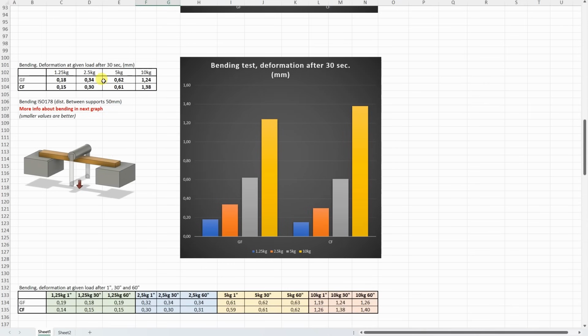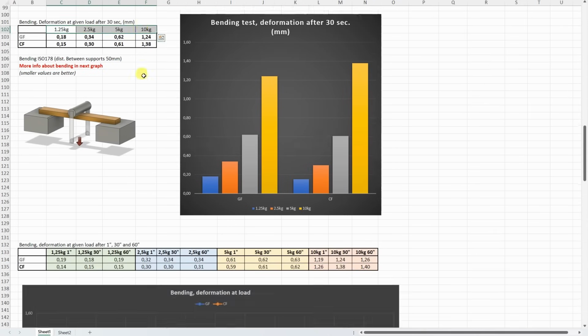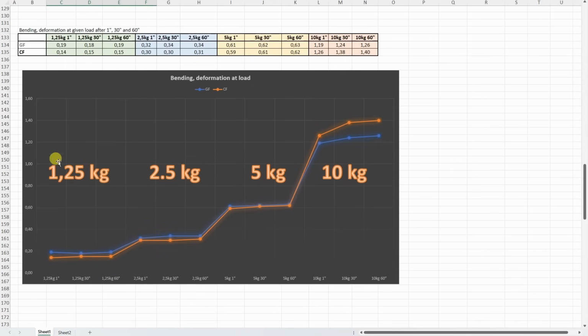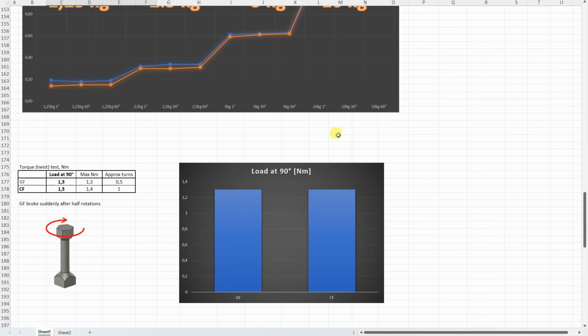And now the bending test. Now this is the deformation under these given loads after 30 seconds, but more interesting is this graph. And here we can see on smaller loads less deformation on the carbon fiber version, because here actually the base material resists to this stress. And look at this, on 10 kilograms, when actually it starts with the bending and the fibers take over the stress, here the glass fiber is better compared to the carbon fiber version, and also the carbon fiber version creeps here a little bit more.